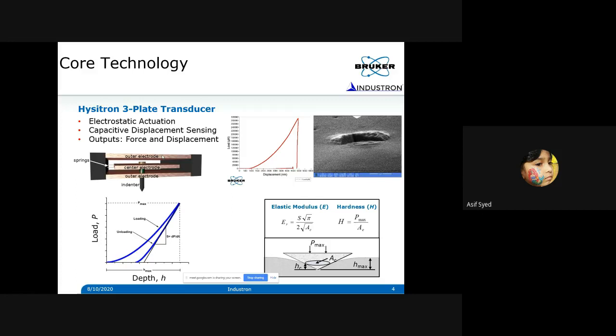Okay. So down here, I've shown the load displacement curve, and this is the loading part. As you load, you go to the maximum force. When you unload, you can see what looks like a straight line, but it is not a straight line. And you can measure the slope of this unloading curve. When you measure the slope, it's basically load divided by depth. It gives you the stiffness. Okay, and stiffness is what you need to deconvolute the mechanical properties from these kinds of curves.